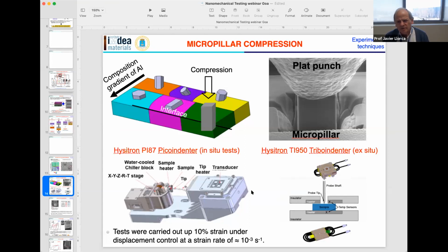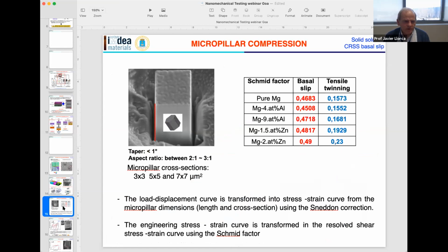Actually, we can go up to close to 700 degrees Celsius, but the results I'm going to present today are limited to 100 degrees Celsius because this is enough for magnesium. In all cases, tests were carried out up to 10% strain under displacement control and at a strain rate of more or less 10 to the -3 second to the -1, so quasi-static conditions. Okay, so let's go to the first case.